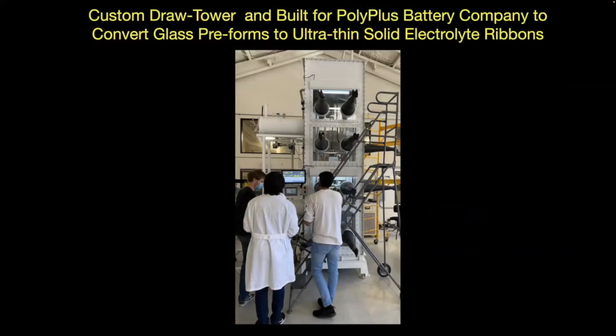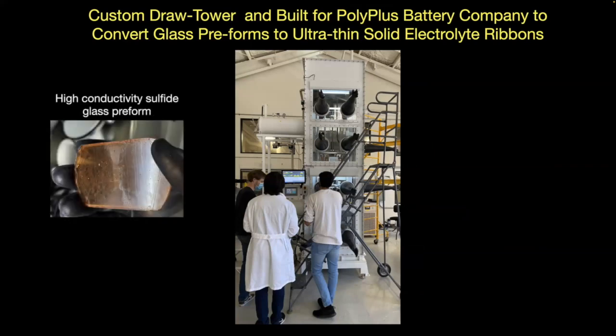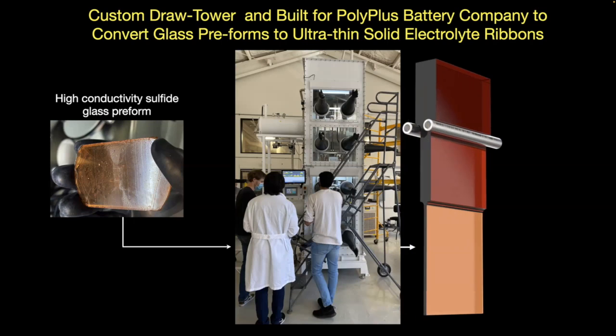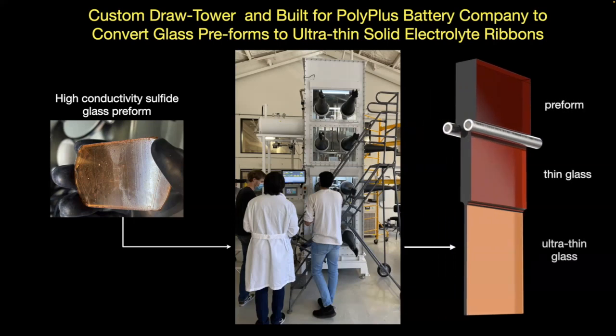And just to show you what that tower is doing, on the left, you can see an actual preform, right? That is a sulfide glass bar, about a millimeter and a half thick. That is then transferred into the draw tower. Inside the tower, we have a set of rollers. The preform descends into a preheater from a furnace, then it descends to the rollers. The rollers then start to roll it thinner. And beneath that process, we have a linear actuator, basically a gripper that pulls the glass even thinner. As long as we control the rate at which we're pulling and the rate of the rollers, we can control the thickness of the glass.